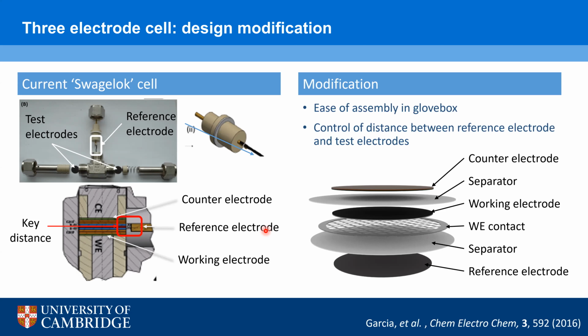and specifically also trying to introduce the use of standard components that we have inside the glove box, in particular using a piece of lithium as the reference electrode. One of the things that we would like to try with our design is, at the moment, at the end of the probe reference electrode, there's a small piece of lithium. If we could use a larger 14mm standard lithium chip, that would also provide a larger surface area, which would hopefully make the behavior closer to the ideal constant potential that Dylan mentioned earlier.